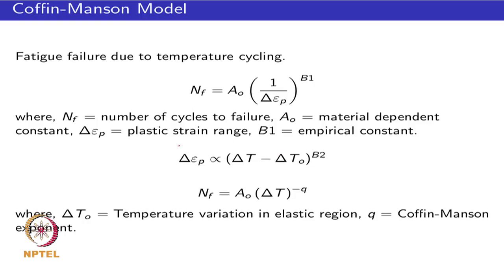Also we know that this particular strain range is proportional to the temperature difference of the cycles through which you heat up and cool down the temperature of the junction. You might have some temperature range corresponding to the elastic stress, and then the balance would correspond to the temperature range where you might actually have plastic deformations. So overall, the delta T naught, which might correspond to the temperature variation in the elastic range, might be quite small compared to the overall temperature variation. So you could simplify it to the form that the number of cycles to failure depends on the variation of your junction temperature to some exponent. A naught and Q are essentially constants.